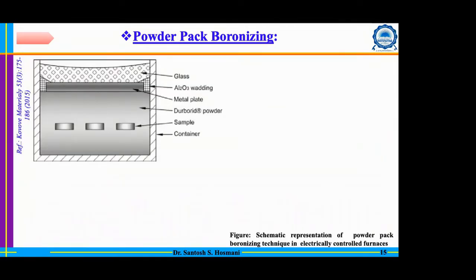So the experimental setup is pretty simple. You have the container, and the material for the container ideally is a steel container. You can go with a mild steel container, even the stainless steel container people widely use. And then in that container, you must adopt a particular mixing process. Whatever layer thickness you are putting of the boronizing mixture, then followed by the alumina powder or even the glass powder, whatever combination you are selecting, that should be uniform throughout your process.